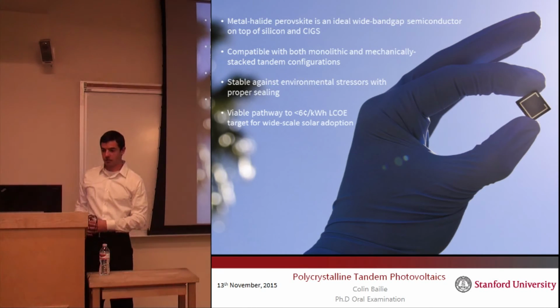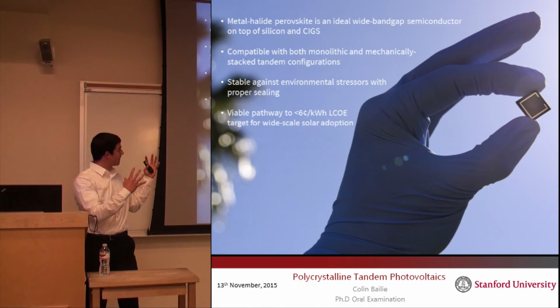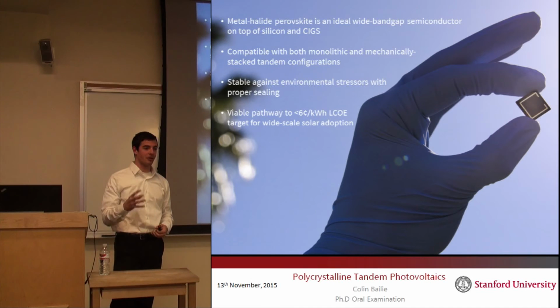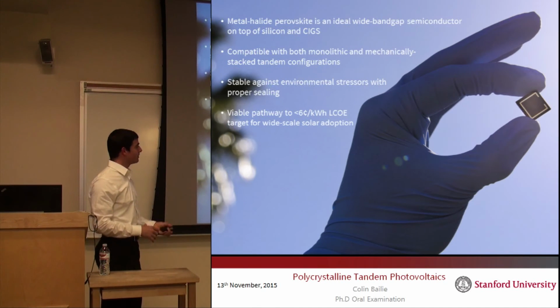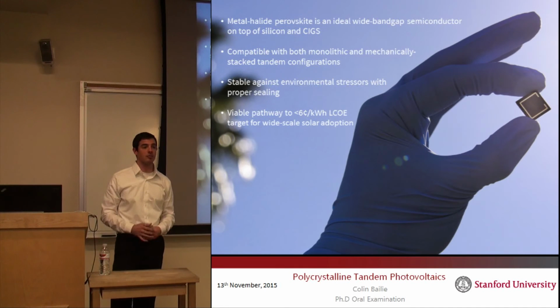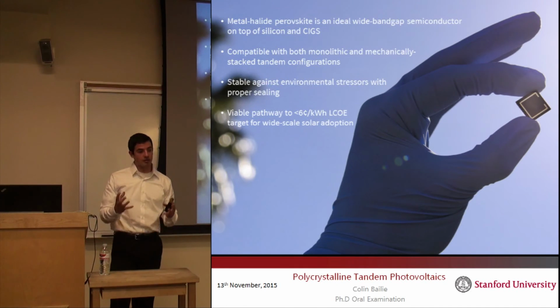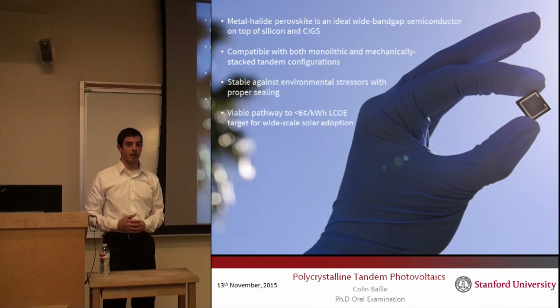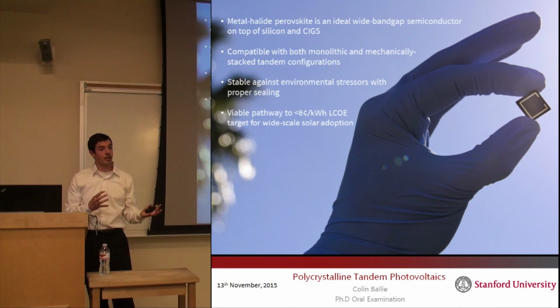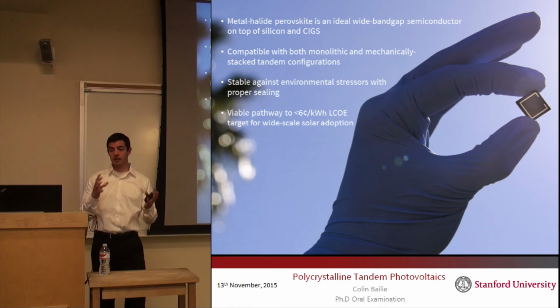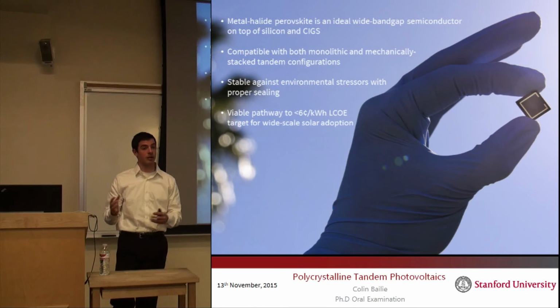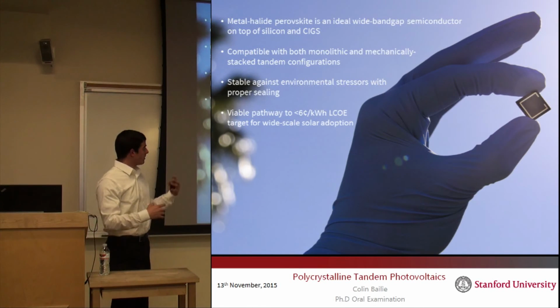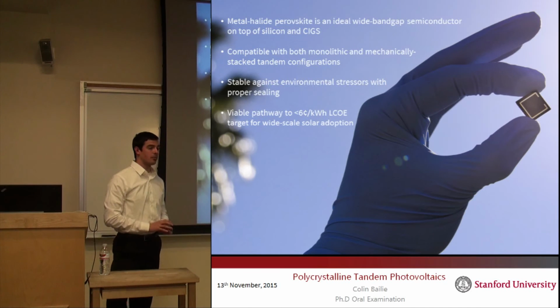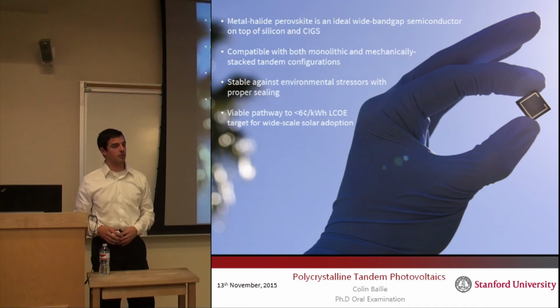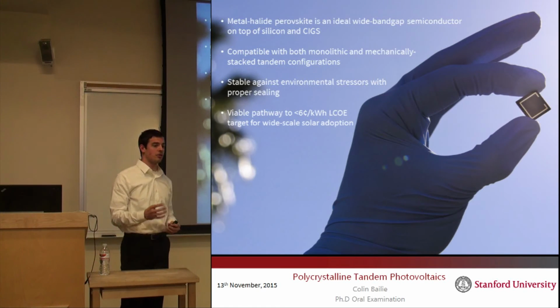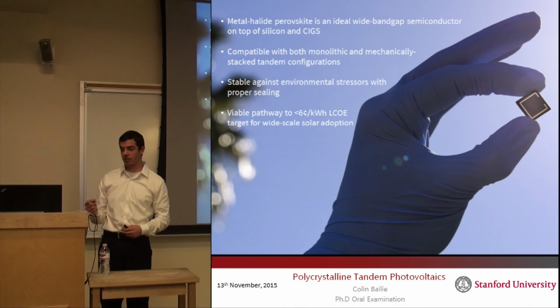So to end, I'd like to leave you with a few final thoughts. I'd like to hope that I convinced you that the metal halide perovskite is an ideal wide bandgap semiconductor for use in tandems on top of silicon and CIGS, and that it's compatible with both monolithic and mechanically stacked tandems, but that these monolithic tandems have a couple of Achilles heels, and that the mechanically stacked architecture gets around these issues. And that there are signs that even though the perovskite has some stability issues, if you seal it properly, then you can make it stable against these environmental stressors.